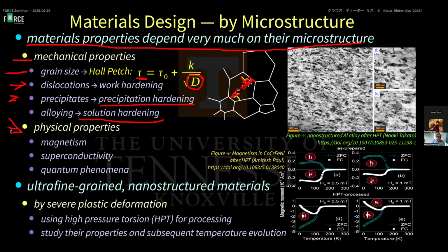The microstructure also determines the physical properties, for example, magnetism. And since we are talking HPT, I have here an example which we studied not so long ago with Amitesh Paul, where the magnetization changes, whether we have HPT processed material or whether we look at the as-prepared material. You can see the differences here in these curves of magnetization. So this is the magnetization as a function of temperature. At low temperatures it changes dramatically, and the character changes a lot. So these are all design parameters.